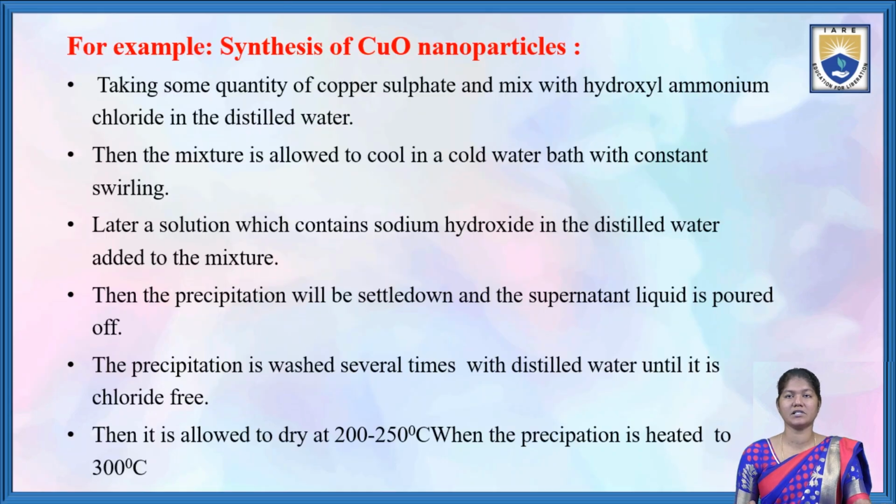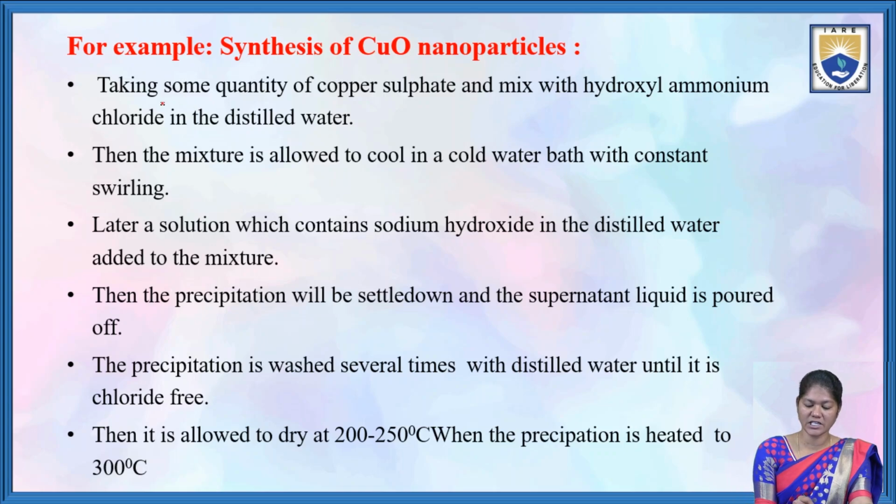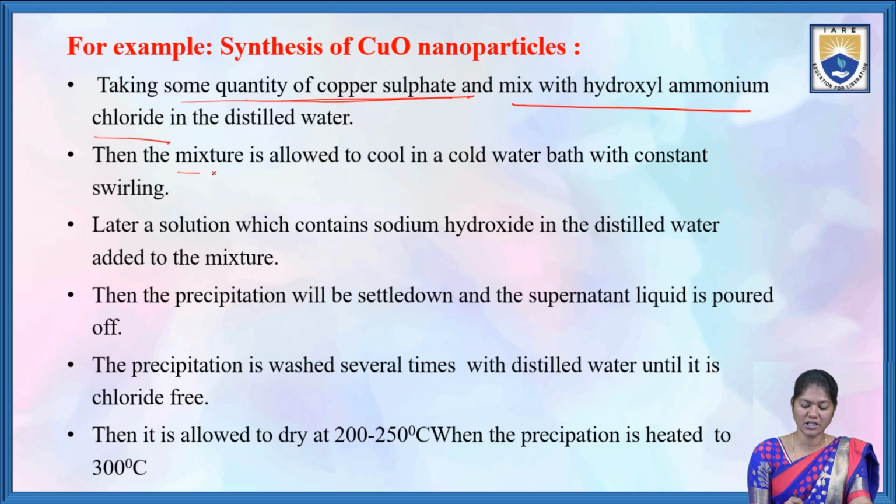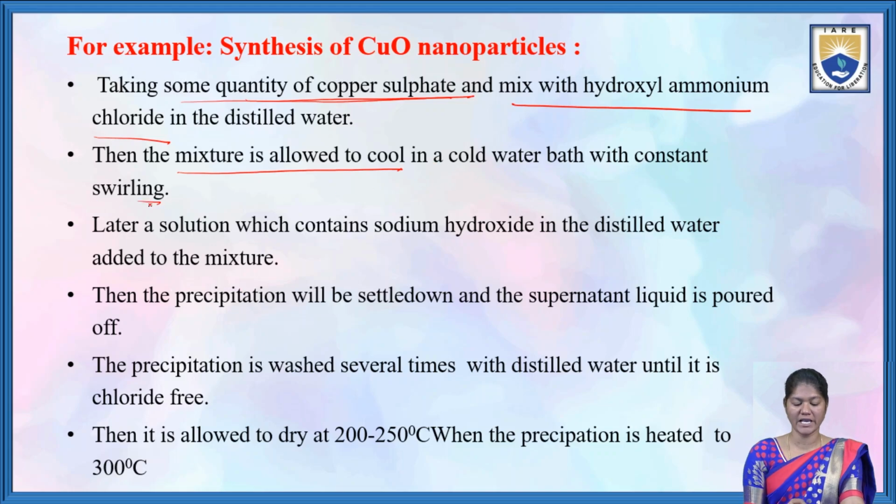For example, for the synthesis of copper oxide nanoparticles, we take some quantity of copper sulfate and mix it with hydroxyl ammonium chloride in distilled water. The mixture is allowed to cool in a cold water bath with constant swirling. Later, a solution which contains sodium hydroxide in distilled water is added to the mixture.